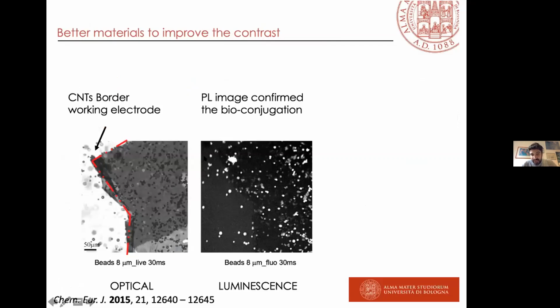But what I would like to show you is that the surface is also a key point in ECL application. In fact, to generate ECL we need to apply 1.1, 1.2 volts for the TPA oxidation, but TPA oxidation strongly depends on the electrode surface. The kinetics of oxidation strongly depends on the electrode surface. And here, we optimize the electrode surface moving from the ITO that I showed you in the slide before towards carbon nanotubes.